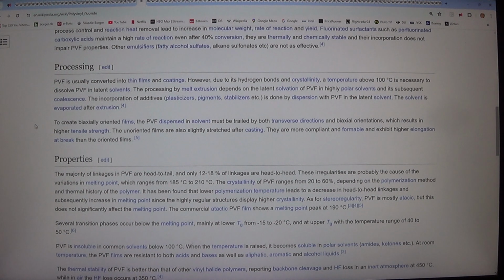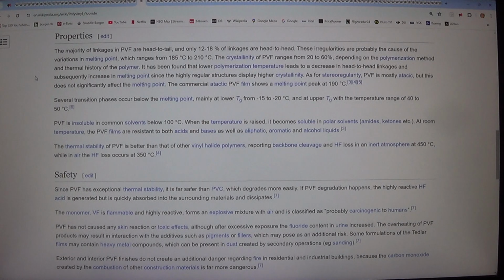Properties. The majority of linkages in PVF are head-to-tail, and only 12 to 18% of linkages are head-to-head. These irregularities are probably the cause of the variations in melting point, which ranges from 185 degrees Celsius to 210 degrees Celsius. The crystallinity of PVF ranges from 20 to 60%, depending on the polymerization method and thermal history of the polymer.